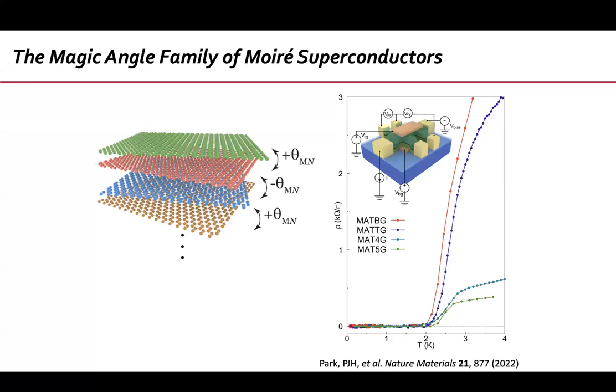Well, no. Tc, first of all, is a little bit higher, not much higher. But if you look at the superconducting coherence, it's actually the same order. It's a substantially stronger superconductor, the trilayer than the bilayer. That doesn't mean that Tc is higher. Remember, you don't measure the strength of a pairing glue by Tc. You have to compare Tc and the Fermi energy, okay? And it is a substantially stronger coupled superconductor. The coherence length in the bilayer is of order 3-4 times the interparticle distance, which is also very strongly coupled. But here, it's like one-to-one.